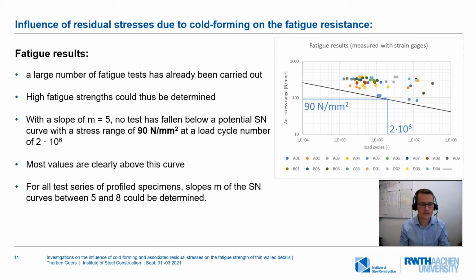The investigations have not yet been fully carried out. However, a large number of fatigue tests has been carried out to date. An assessment of the influence of residual stresses is still pending, but according to the nominal stress concept, high fatigue strength results overall. All results were above a value of 90 Newton per square millimeter at 2 million load cycles. As you can see, most of the values are clearly above this limit. For all individual test series, the slope of the SN curves ranged between 5 and 8.